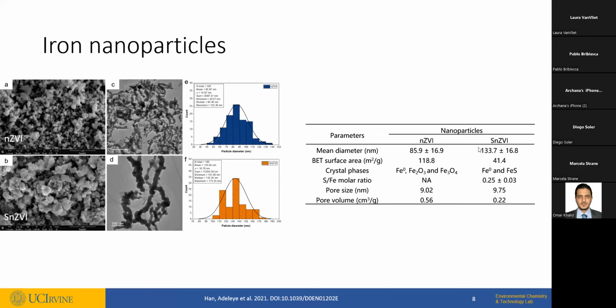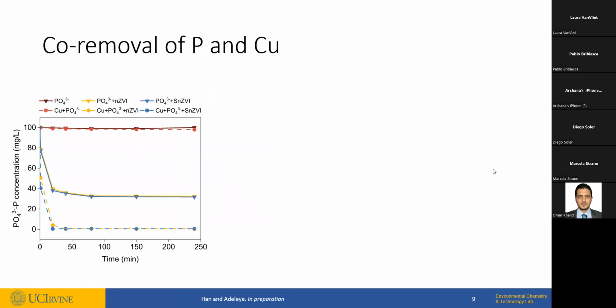With sulfidation, the size increases, and that also means the surface area decreases, and you can see some of the phases of iron in the two nanoparticles. So NZVI has a core of zero valent iron and a shell of iron oxide, while SNZVI is not a core-shell material, it's a mixture of zero valent iron and sulfide species of iron. So real quick, this is what we found when we replaced GAC with the nano iron particles.